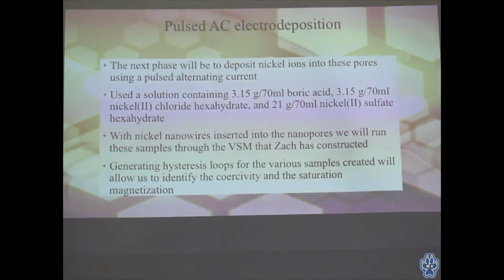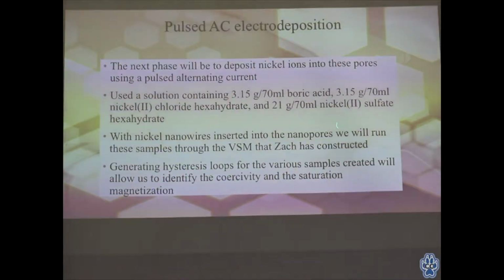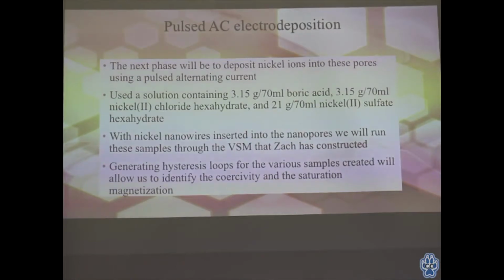So after we were able to recreate these highly ordered, thinned out samples, we wanted to use a pulsed alternating current to electrodeposit nickel into these pores. We used a solution containing boric acid, nickel chloride hexahydrate, and nickel sulfate hexahydrate, which is essentially just an electrolyte with very high nickel concentration.